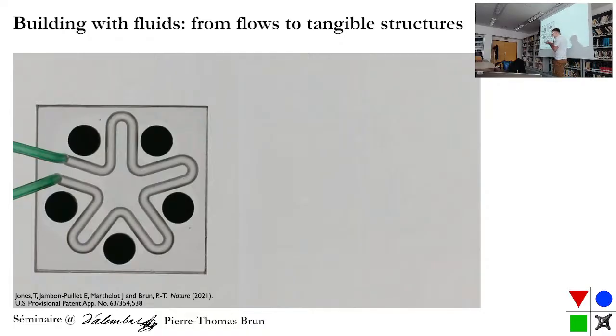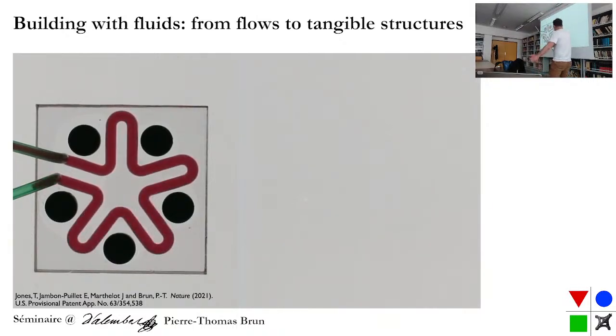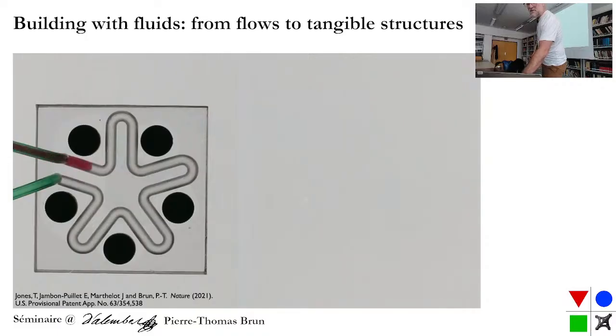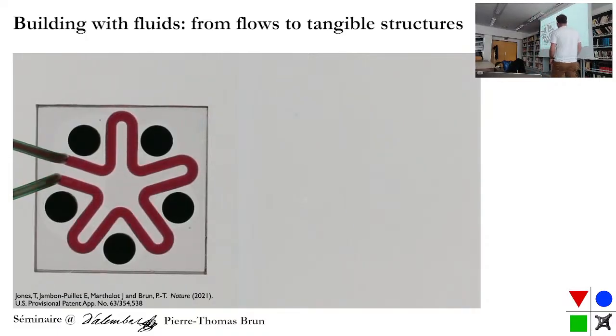And this tube is made by carving 2 half cylinders into 2 acrylic plates. So we have 2 acrylic plates, 2 half cylinders, you put them together, and that forms this thing. The black stuff are screws. But for the purpose of this presentation, this is essentially a tube that has a tortuous path. And so what I do, and I'll show the movie a couple of times, is I inject this elastomer that we've been talking about. And after I'm done injecting it, I push some air the other way around. So I play again, you will see the elastomer invading the space. And then as you push the air, you see a bubble moving quite quickly through this network. Okay, that's the end of the active part of the experiment.